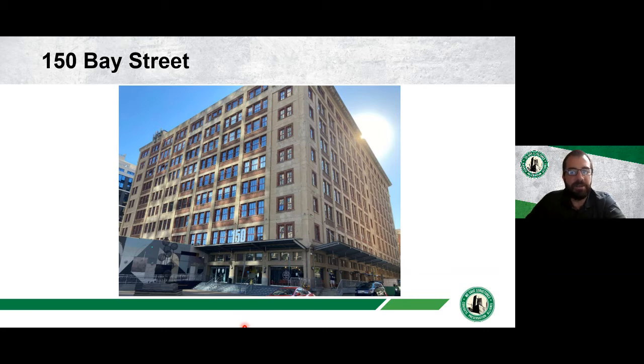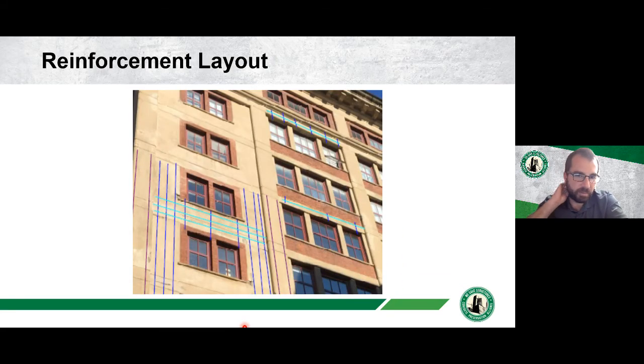So one of the things we were asked to do is evaluate the structure, what the corrosion problem was, and then develop some rehabilitation solutions. One of the things was they didn't know the reinforcement pattern. So using ground penetrating radar, we looked at the concrete and laid out where the rebar is. You can see where this lintel beam is. There's one rebar across and a couple of vertical. You have the columns here with some vertical and then a beam here with several horizontal rebar. So we can go through that whole structure and identify where the reinforcement is, so we know how to design a corrosion mitigation solution.